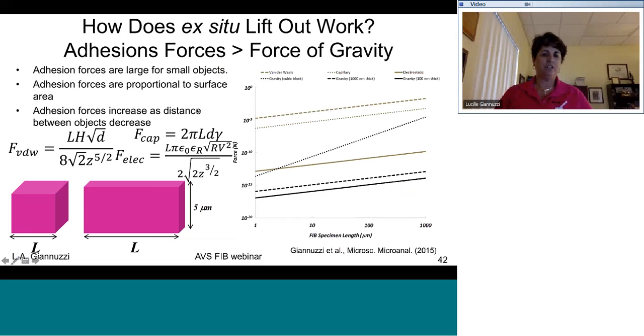Back in the day, people asked us, how does this work? Is this electrostatic forces? And we kind of just shook our heads and said, okay, sure. But most recently, I went back and actually looked at adhesion forces. And it turns out that it's van der Waals forces in play. So here, if we plot on a log scale of the adhesion forces as a function of FIB specimen length, it turns out that the van der Waals forces are actually the strongest, the capillary are somewhat weaker, and the electrostatic forces are actually the weakest of all adhesion forces.